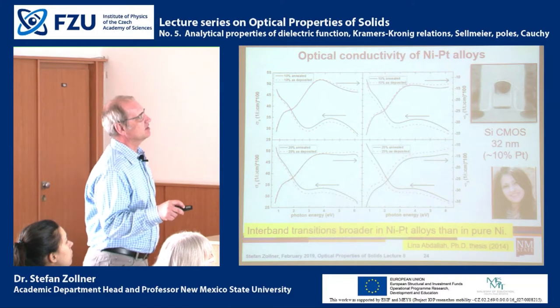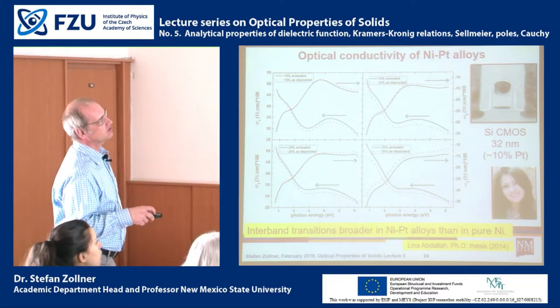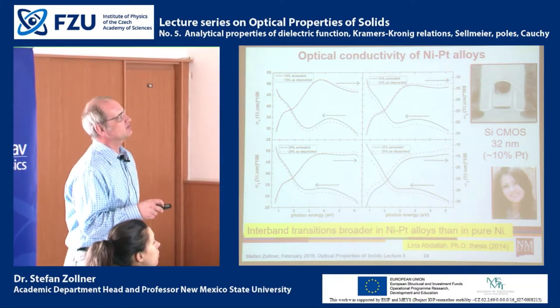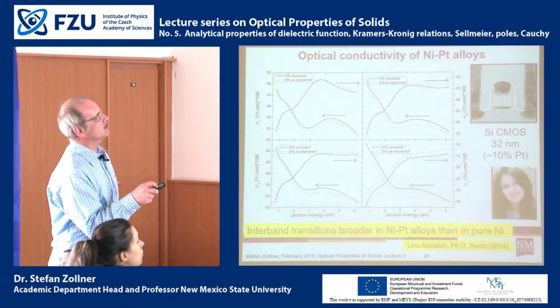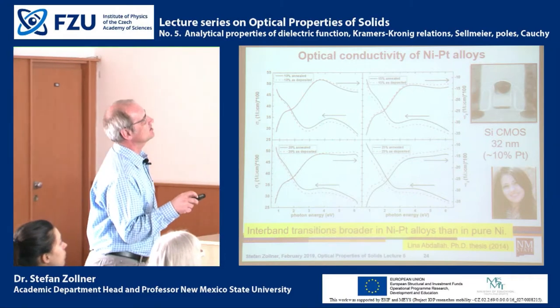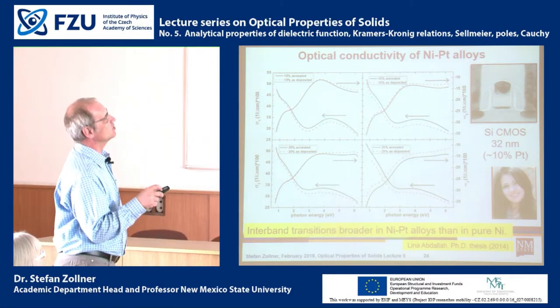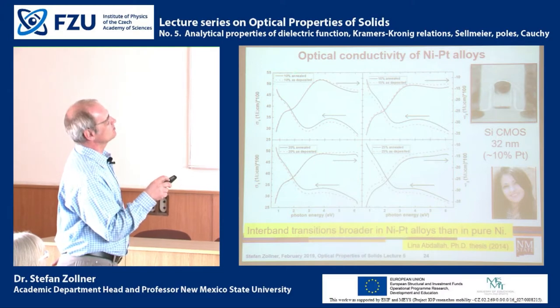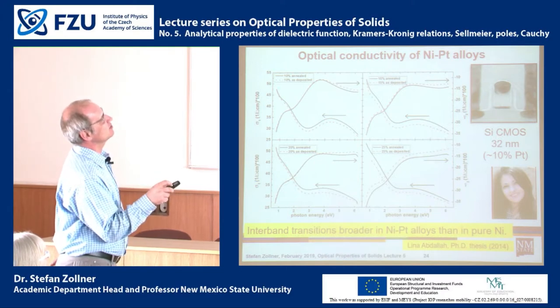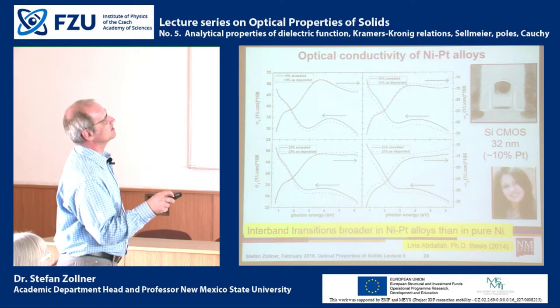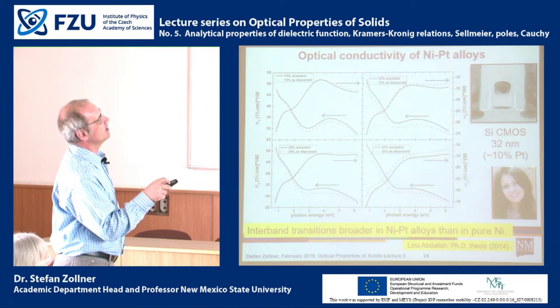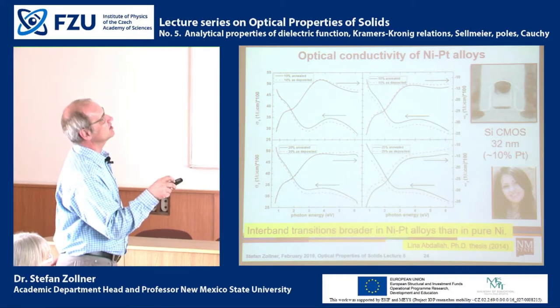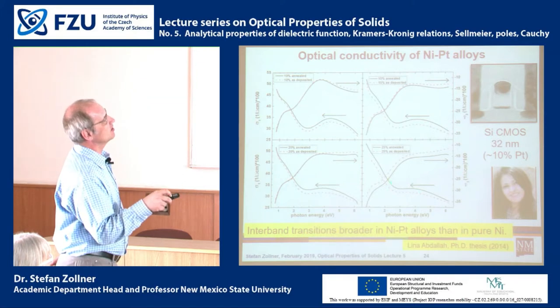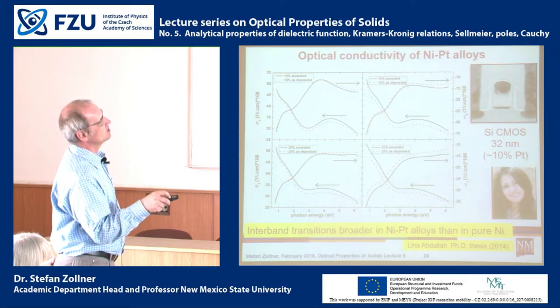And then Lina Abdallah, who was my first PhD student at NMSU, measured the optical conductivity for nickel-platinum alloys with different compositions. So here we have 10% platinum, 15% platinum, 20% platinum, 25% platinum. For 10% platinum, we see quite a pronounced peak, but as we increase the platinum concentration, this peak gets broader and broader.